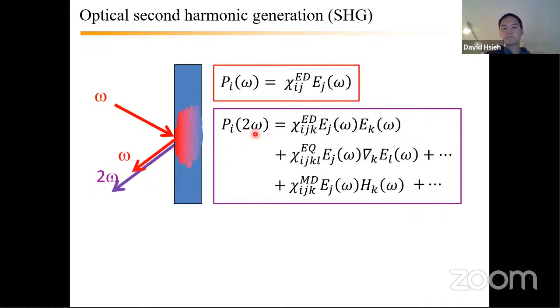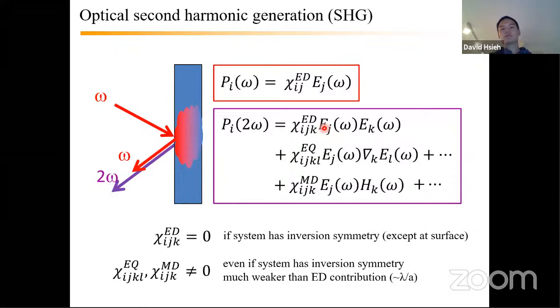However, it turns out that having a bulk response in the electric dipole channel is not universal. In particular, if your system has inversion symmetry, if your crystal has a center of inversion, then this leading electric dipole response is identically zero by symmetry. So then you have to start to consider higher order terms, one of which is a surface electric dipole term. Since the surface breaks inversion symmetry, you can have a non-zero chi ED at the surface, but because there's much less volume there than the bulk, typically that's a much weaker response than you'd get in a bulk inversion-broken material. And that surface response can often be of comparable intensity to higher rank bulk multipole responses.